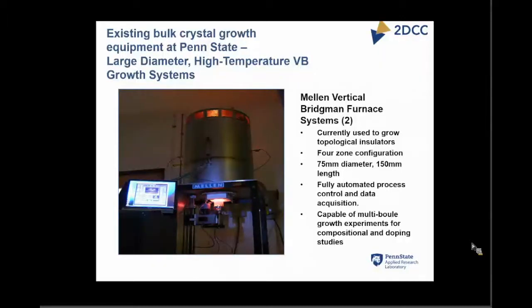But it's ideally suited for looking at things like doping studies, compositional studies, where there's only a slight difference in the melting point. What this really does is allow you to quickly look at parametric studies over a wide range of composition or doping in these materials and get samples in a single run. And so this is what we've implemented for a variety of materials over the years. And this furnace has been configured to be able to do that.